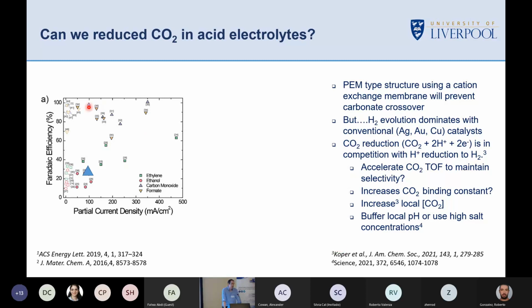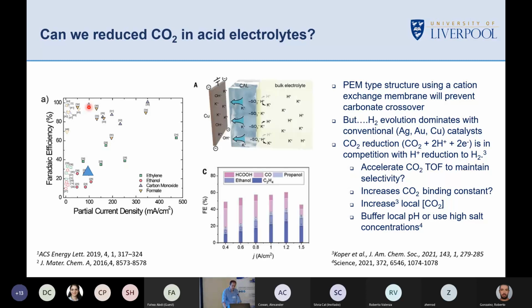The other thing we could try and do is increase the amount of CO2, or we could try and buffer the local pH, and that's what Ted Sargent's work does. It's a very nice approach, but we still need to be aware that we're going to get local carbonate formation with the problems I've just talked about. Or we could try and improve the catalysis of the actual CO2 reduction catalyst, very much along the lines of Mark's suggestion, and try and out-accelerate the hydrogen evolution. And perhaps this is where a molecular electrocatalyst could work. We can tune the local binding environment.